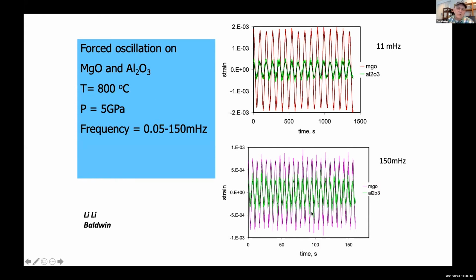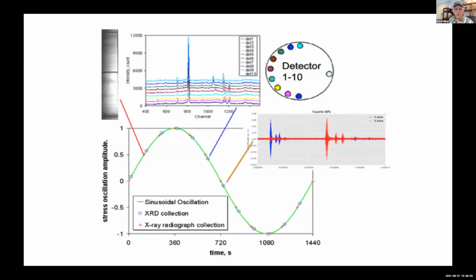And you can see in these two images, one with 11 millihertz and one with 150 millihertz, that the ratio of the amplitudes are different. And the conclusion of this is that the effective Young's modulus with a 100-second period is lower than that of the Young's modulus of MgO at 10 seconds period. So this kind of experiment we can use for looking at dispersion of elastic properties. And this is in the range where we have very low amplitude vibrations.